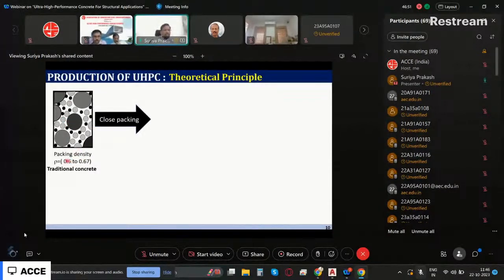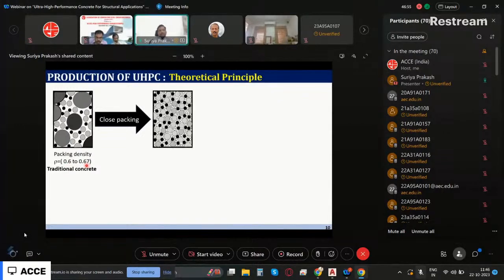For normal concrete, the packing density is about 0.6. But what we are trying to get in UHPC, by limiting the size of the particle, is to pack all small particles of different sizes so that I can reduce the white spaces inside the cross section. So if you look at it, these white small particles are all particles, and whatever space there is between them, that is your void.